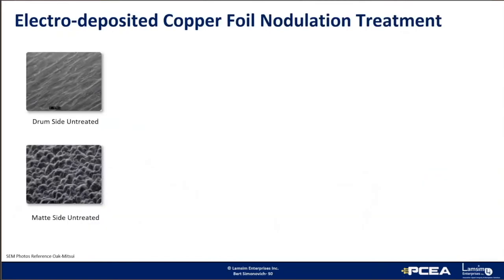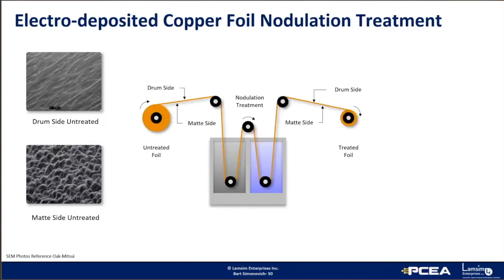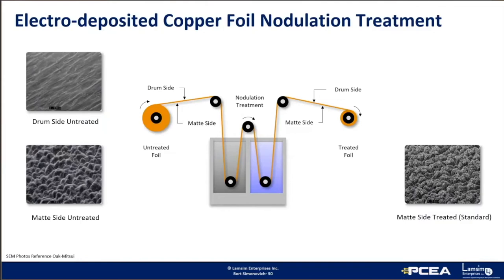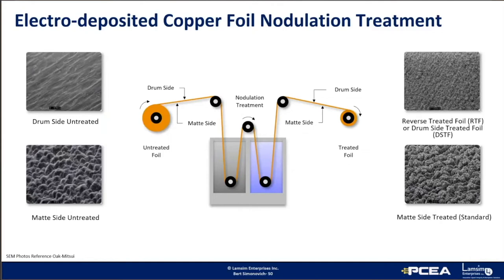After coming out of the electro-deposited fabrication process, the drum and matte sides of the foil look something like this. The foil then goes through a nodule treatment process where tiny nodules are deposited on one side of the foil. The standard process deposits tiny nodules onto the matte side of the foil, shown here. But when nodules are deposited onto the drum side, it's commonly known as reverse treated foil or drum side treated foil.